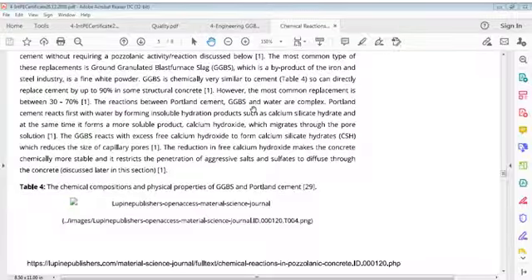Portland cement reacts first with water by forming insoluble hydration products such as calcium silicate hydrate, and at the same time it forms a more soluble product, calcium hydroxide, which migrates through pore solution. GGBS reacts with excess free calcium hydroxide to form calcium silicate hydrates, which reduces the size of capillary pores. A reduction in free calcium hydroxide makes concrete chemically more stable, and it restricts penetration of aggressive salts and sulfates to diffuse through concrete.